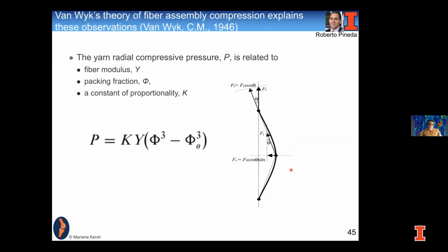But we know that the compressive pressure in the yarn is related to a couple of things that we could actually measure: the fiber modulus, or look in the literature for the packing fraction, so how much yarn there is within a given area, and then, like any good model, a proportionality constant to help us.